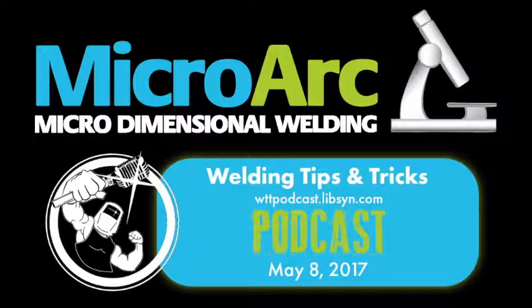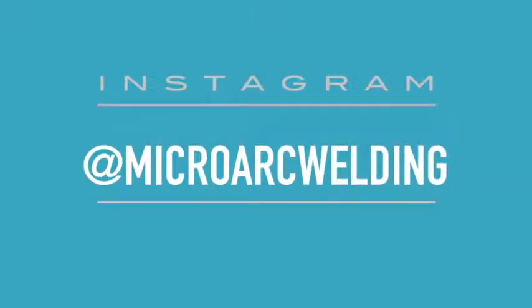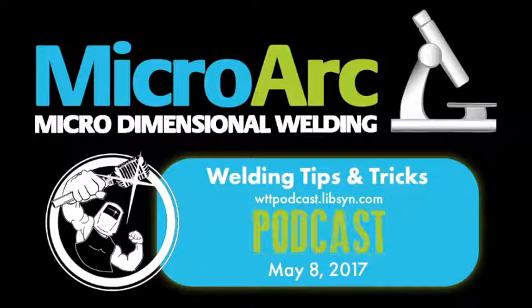It's crazy. Not easy. When we're using that type of wire with the TIG, we literally hold a 2 to 3 thousandths tungsten to puddle gap. So when I'm welding micro TIG under the scope, I have probably about a 3 thousandths gap or less. Jeez. Because I thought I held a tight arc. Yeah, you do. Wow. 2 thousandths. You do, Roy. Come on.